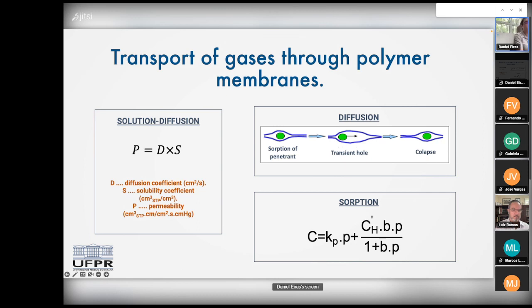The sorption, that basically means absorption and adsorption. The sorption in polymer membranes is explained by what we call the dual mode sorption model, which means there are two populations of spaces where you can sorb a gas molecule in a polymer material. One is modeled by the Henry parameter, that is the kD, and the other is the Langmuir. So Henry basically is absorption, and Langmuir would be adsorption. The gas molecule is strongly absorbed by the Langmuir spaces, and the interaction is a little weaker for the Henry spaces. So this is basically how we model or explain the permeation of gases in polymer membranes.